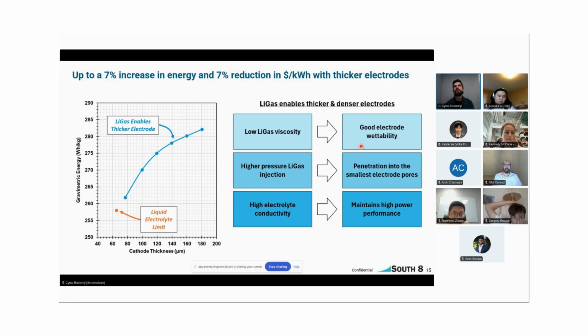Well, if you imagine your liquid electrolyte, it's a higher viscosity solution. When you add it to these thicker electrodes, it doesn't wet that entire electrode very well. It leaves a lot of gas pockets. You don't really get the power you need out of that cell, and your cycle life goes kaput very quickly. With South8's liquefied gas solution, the solution has a significantly lower viscosity, probably about an order of magnitude, which enables very good wettability into those electrodes.